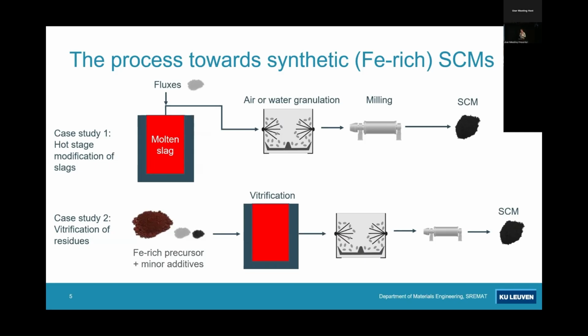We add something to the slag that makes it more amorphous after granulation and more reactive as a cement substitute. Then we have a second case, which is the use of tailings. In this case study, bauxite residue, to vitrify this material and cool it down very fast and create a Portland cement substitute. These processes reduce the amount of CO2 emissions because you don't use that much limestone, and it's also interesting because you can valorize quite some byproducts which are now used in low-grade applications or even not used, for example bauxite residue.